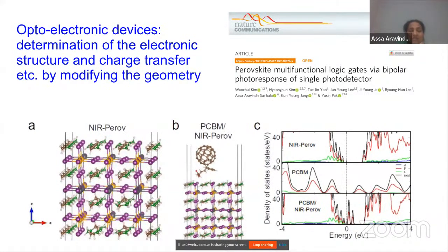Okay, so this is mainly an experimental work, but they have to understand why this is happening when they do this kind of geometry, how this molecule is orienting, and what is happening to the electronic transport. And I supported this with DFT, and what we have seen is when this molecule is oriented in a certain way, for example, with the tail facing down towards this MAPI surface, then there are significant electronic states coming into the band gap, which is helping the electronic transport property. So DFT can act as a very important tool to explain experimental phenomena and help the experimentalists explain the results.